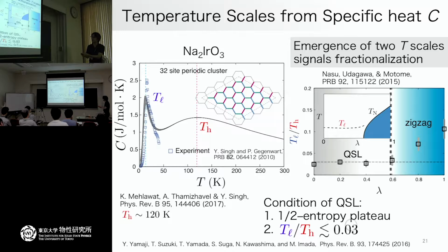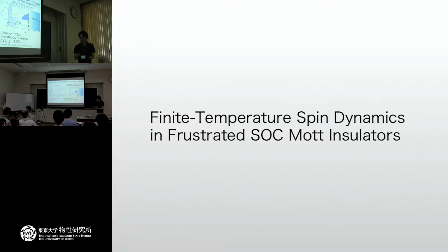It's formulated like this. This ratio should be smaller than 0.03. However, maybe many of you already know the heat capacity measurement is really difficult, because if you're measuring the heat capacity in a lattice system, you will have a lattice contribution in the heat capacity. And the subtraction of this heat capacity from the lattice degrees of freedom is not so easy. So in this sense, we need much more information about the finite temperature signature of the spin liquid phase.